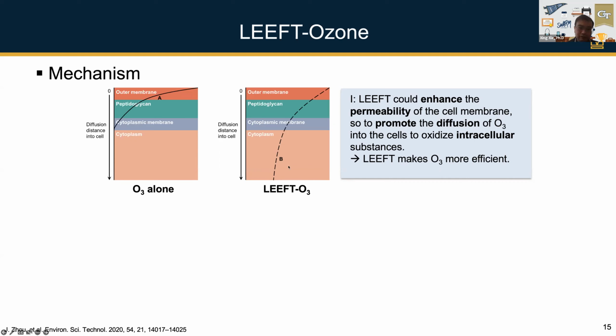But if you do the LEEFT first, even though they don't get killed, you significantly increase the permeability of the cell membrane. So you significantly increase the diffusion of the ozone into the cells, and that makes the ozone much more effective in terms of killing the pathogens, killing the microorganisms.